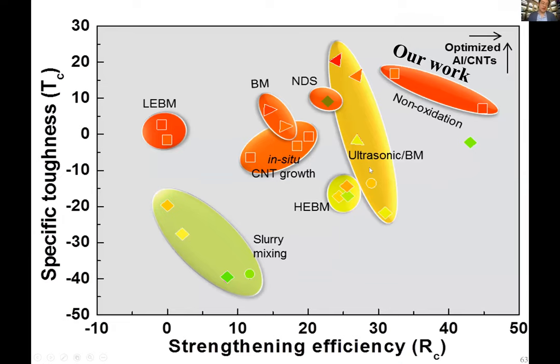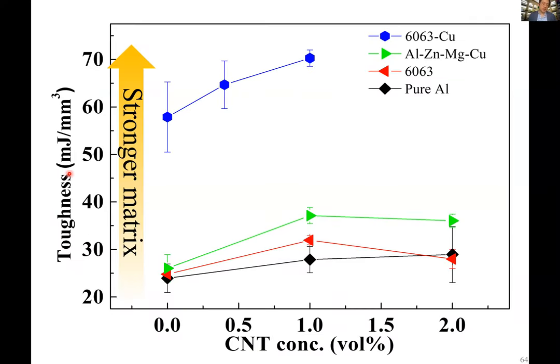So what we show here is that previously, there were different ways of making carbon nanotube nanocomposites: high energy ball milling, in situ carbon nanotube growth, slurry mixing, low energy ball milling. But in our approach, we're able to strengthen the material in yield strength by 40% without sacrificing the ductility, where most of the other approaches would embrittle the material. So what we show here is toughness. And this is not only true for pure aluminum; we have also used pretty high alloy 6000 series aluminum alloys, and you still have a very potent strengthening effect, as well as improving the tensile toughness of the composite.